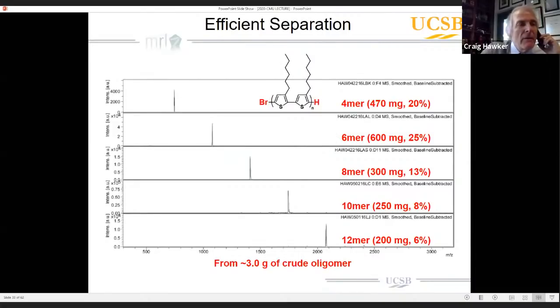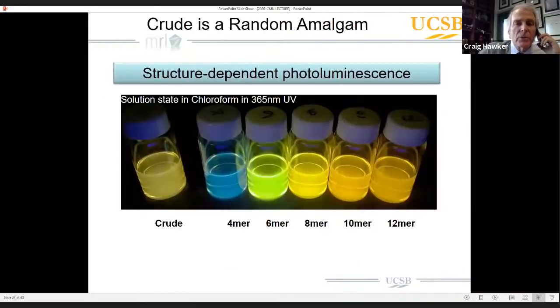Again, we're getting very high retention of the mass. We're also getting samples that have reasonable quantities, all in the hundreds of milligrams from the tetramer all the way up to the dodecamer. And again, you can synthesize the dodecamer using a stepwise strategy, but it's about 12 plus steps and the overall yield is extremely low. Here we're getting it in a single step. And so this was a real, I think, big step forward in terms of oligomer chemistry.